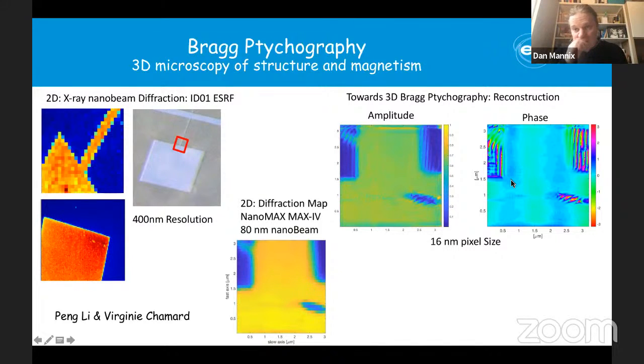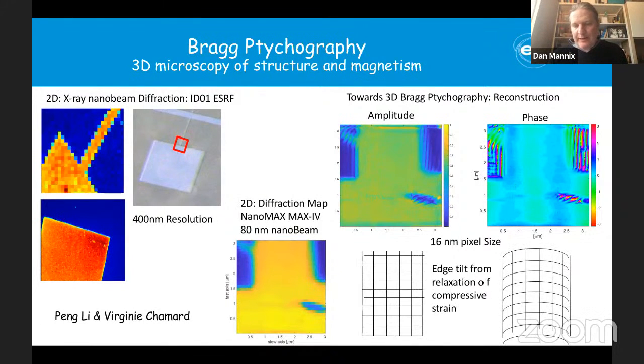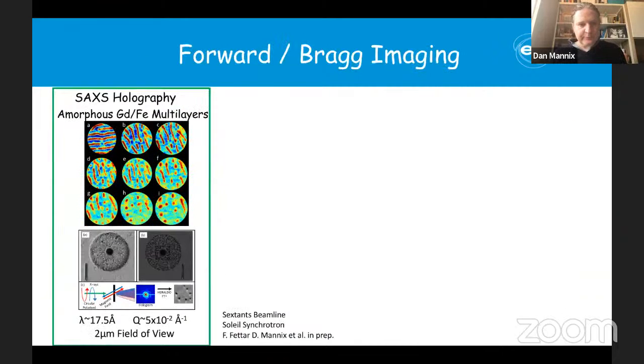This is still preliminary data, but one aspect is that it could be due to some kind of tilting. As you've cut out those wires by lithography, and because they're under compressive strain, this can lead to some sort of tilting towards the edge. This is information that we didn't know before we started ptychography at all, so that's already very promising.